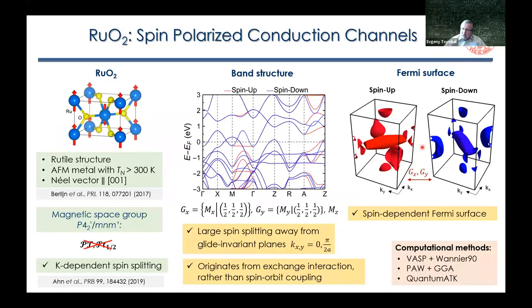So you can imagine that now, instead of this perpendicular direction, you have, let's say, this direction. And obviously, if I go along this direction, there is a huge asymmetry as compared to this case. It was already mentioned in a number of previous publications that if you think about conduction along this direction, there should be some spin asymmetry, even in the bulk antiferromagnet, if you neglect spin-flip scattering processes. So I think that should also be reflected in tunnel junctions, but whether the effect will be stronger or weaker is hard to claim immediately. A specific calculation is needed to look at this, but certainly there will be some effect, no doubt.